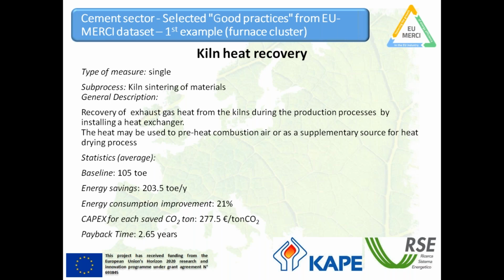You've got the average statistics here. So baseline around 105 TOE, around 203.5 TOE per year energy savings. Energy consumption improvement was found to be on average around 21, 277.5 euro per ton of CO2 emission avoided, and a payback time of, on average, 2.65 years. So the payback time is pretty acceptable.